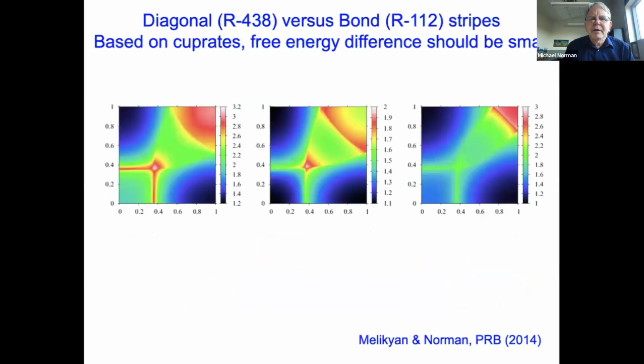And people have noticed that in the doped 112 materials, you typically see bond-centered stripes, whereas in this 438 material, you see diagonal stripes. But from old work that we did in the cuprates, the free energy difference between diagonal and bond-centered stripes is actually pretty small. And so it's pretty easy to go from one to the other. In one case, you have a wave vector near 1/3 0, and in the other case it is near 1/3 1/3. So the wave vectors are saying you just rotate. You can see, again, these are susceptibility plots for various tight binding dispersions. And the susceptibility has a typically box-like structure around the gamma point, which basically means that there's not much free energy difference between a 1/3 0 stripe and a 1/3 1/3 stripe.